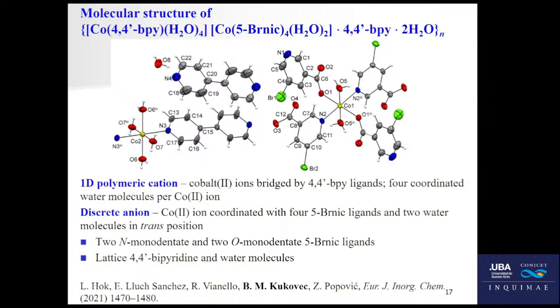As an anion, we have a discrete cobalt complex composed of a cobalt ion, shown here, coordinated with four 5-bromonicotinate ligands: the first one, second, third, and the fourth one. Two of them are N coordinated, and the other two are O coordinated. And as I said, we also have additional, you can see it here, co-crystallized or lattice 4,4'-bipyridine ligands and water molecules.